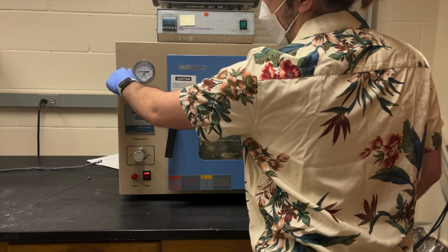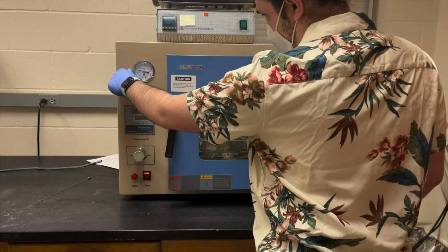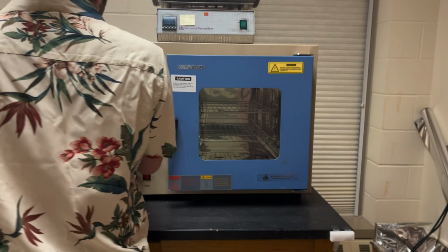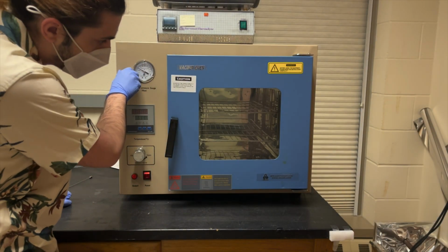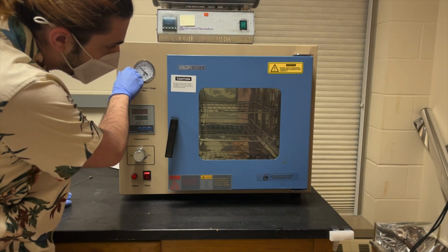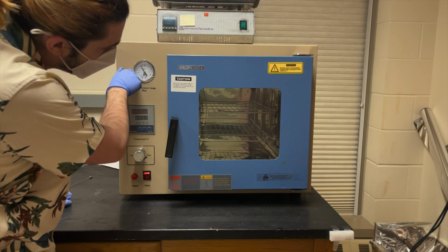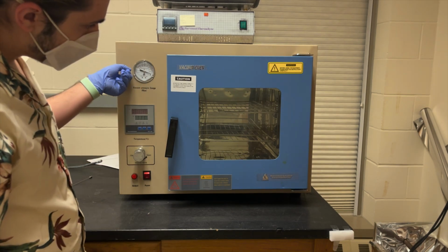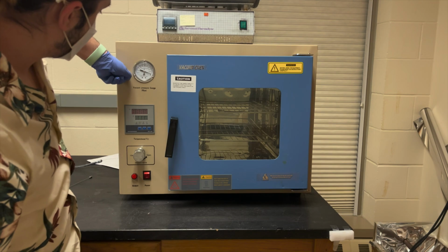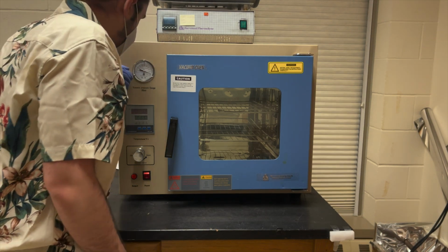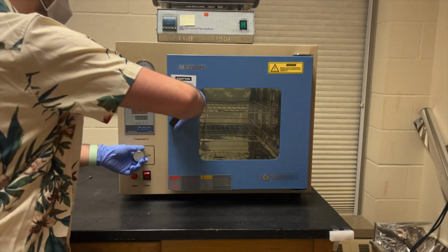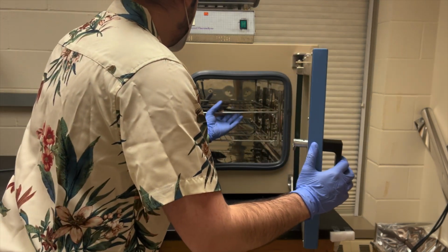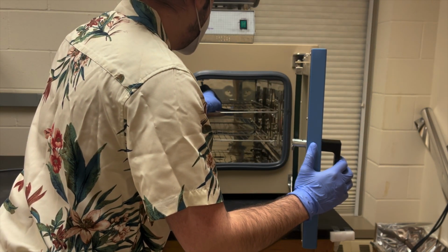It's important to vent slowly, otherwise the rapid change in pressure will cause your foil to fly around and may result in damage or reduction in quality. Once the oven is at atmospheric pressure again, we will close the vent valve and remove our casted foil from the oven.